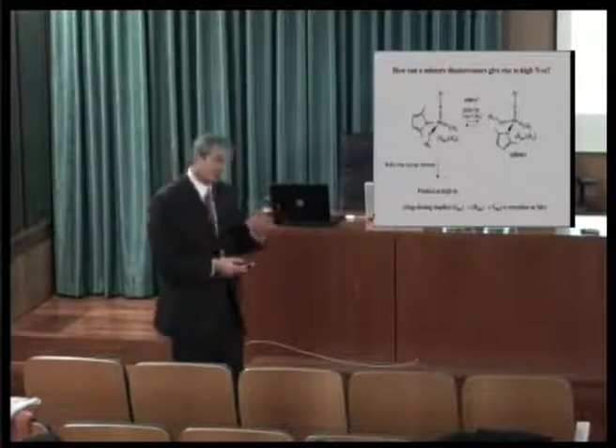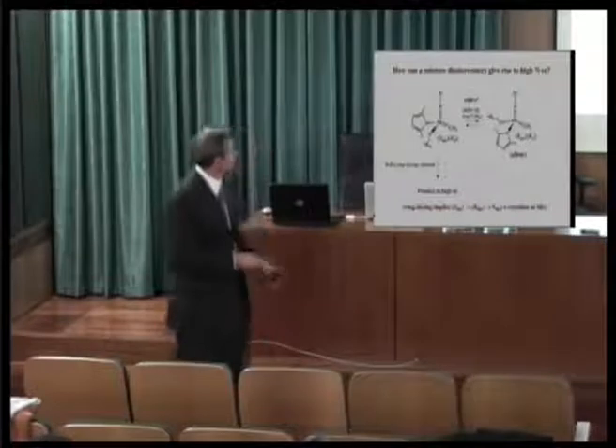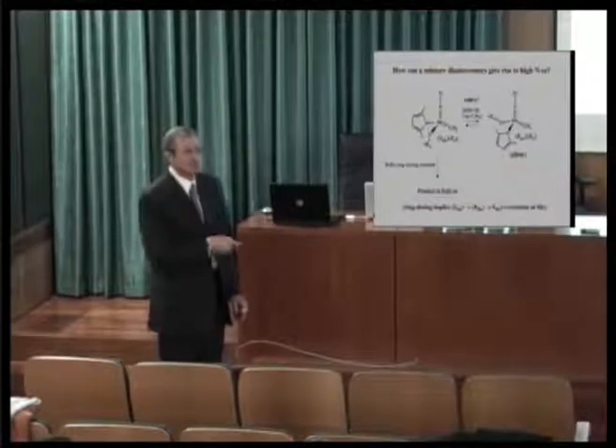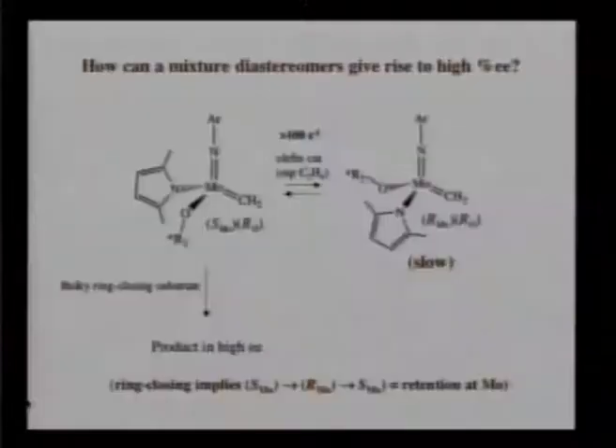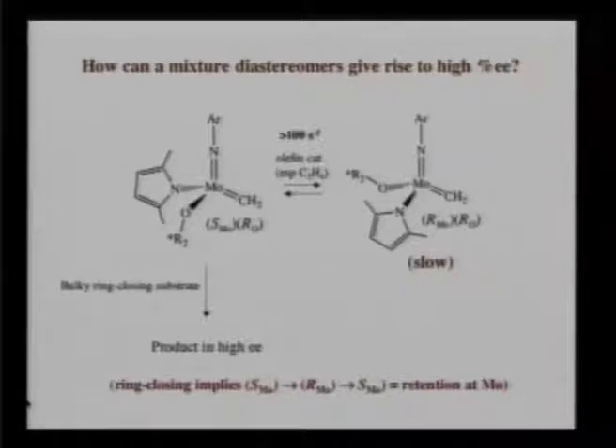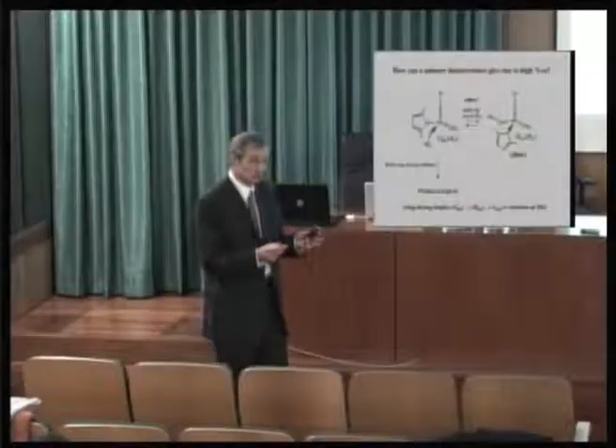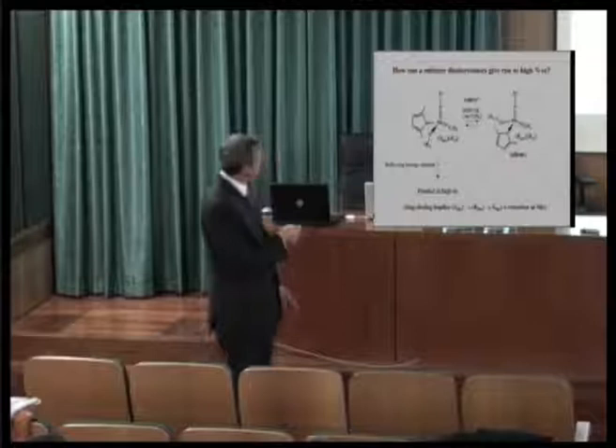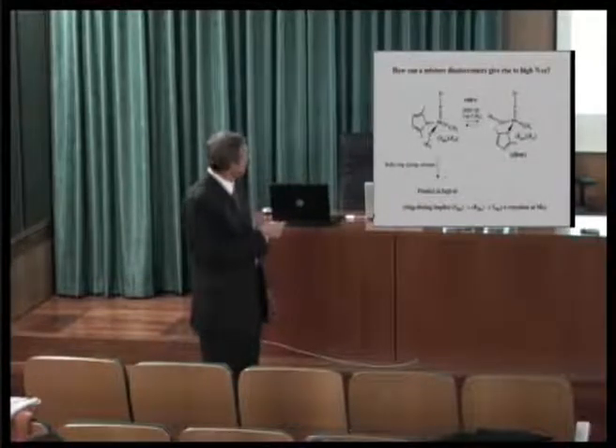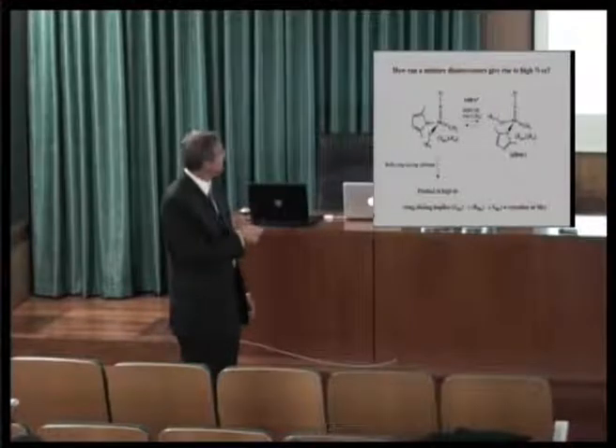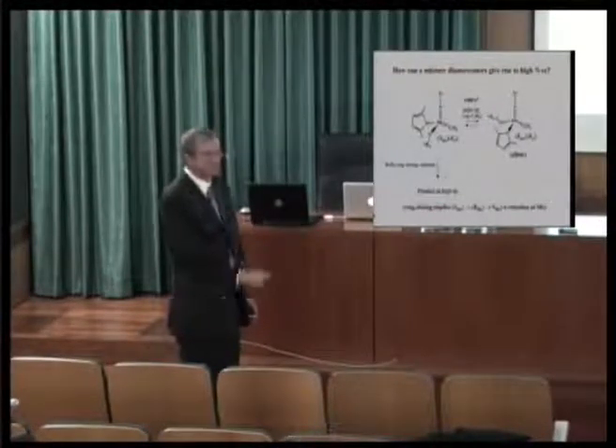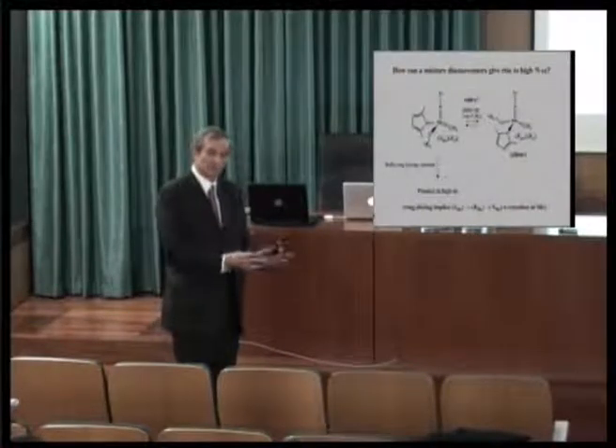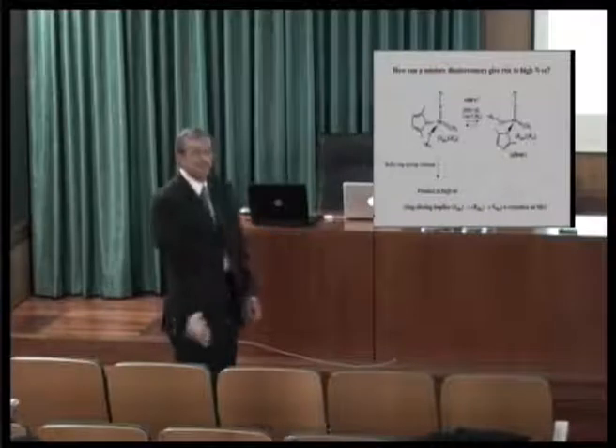Well, it's a very now pretty well understood general phenomenon where you have 2 species in equilibrium, the 2 diastereomers that are possible. I show them as methylene species here for simplicity, the one that is S at the metal, and then the chirality in the ligand, or R at the metal. But this one basically is a relatively slow catalyst. We don't know whether it's absolutely slow, but it's relatively slow. It's converted readily into the fast one, and the fast one gives product in high ee. So the answer is that only one of the 2 diastereomers is reactive enough to make product, and it makes it very well, very high ee.